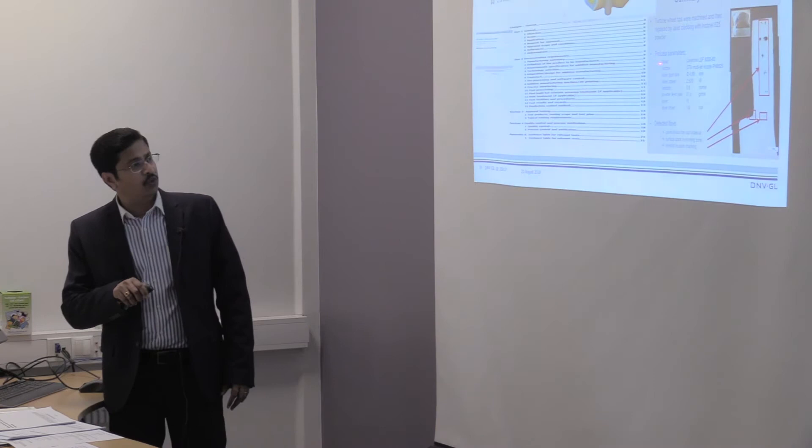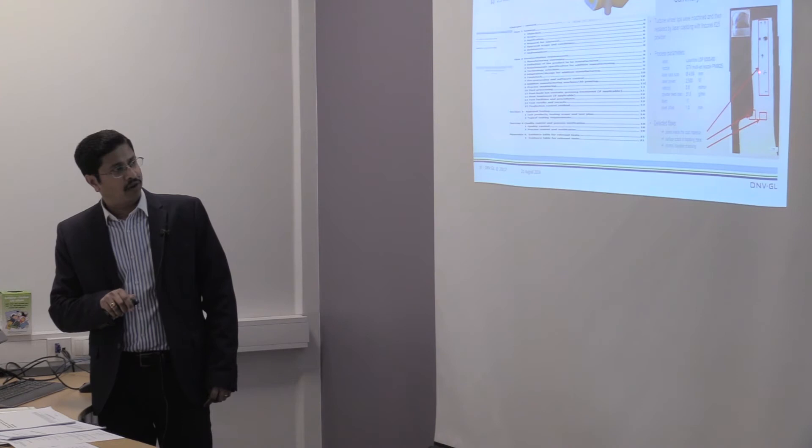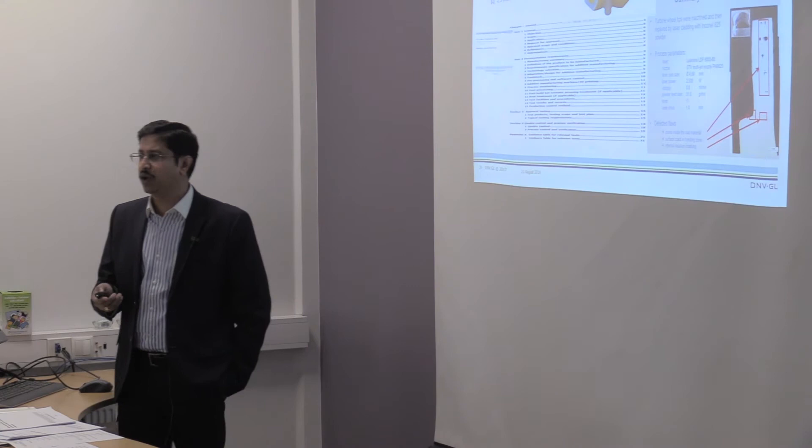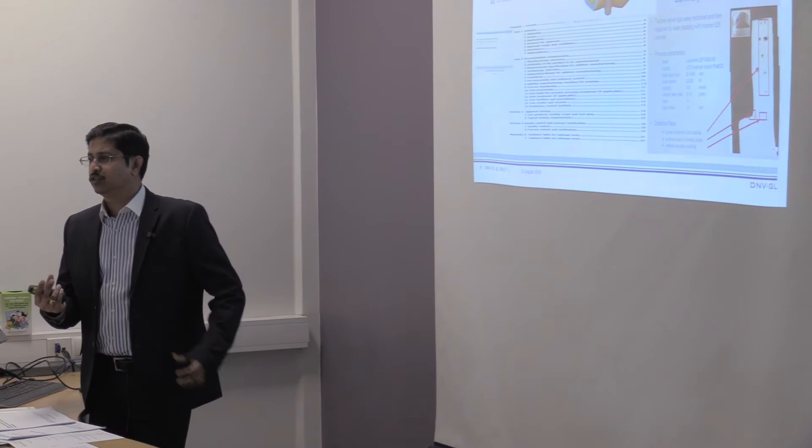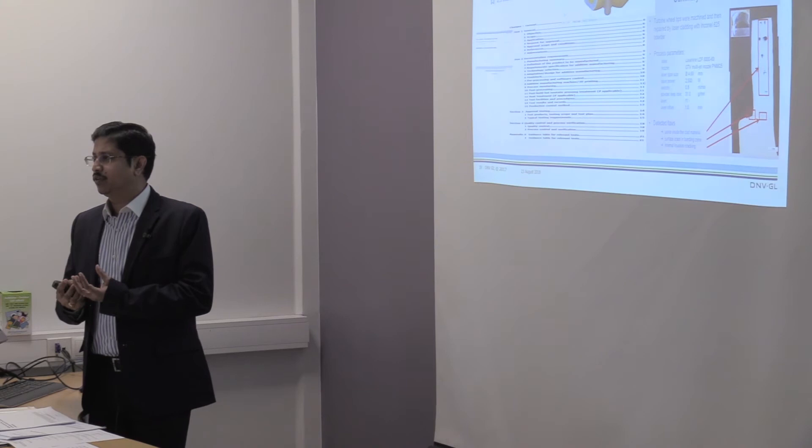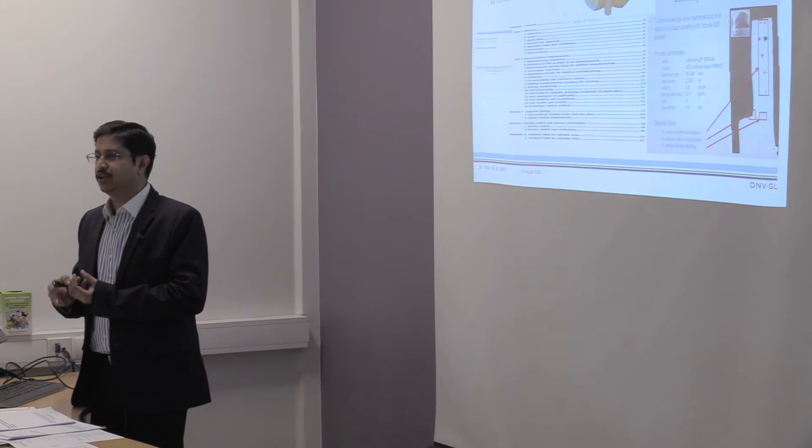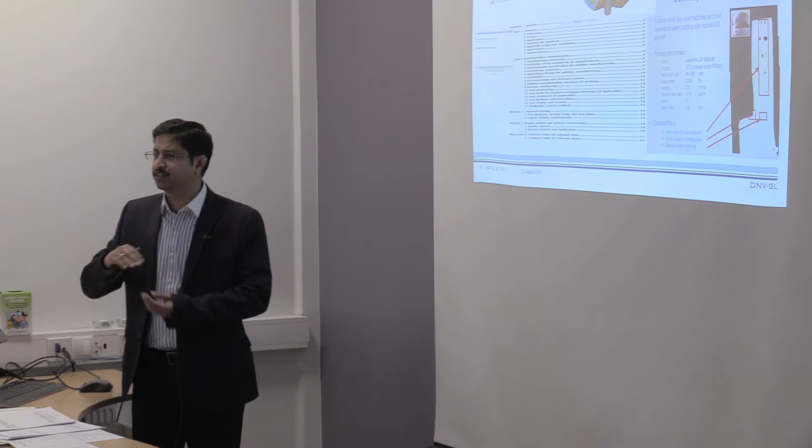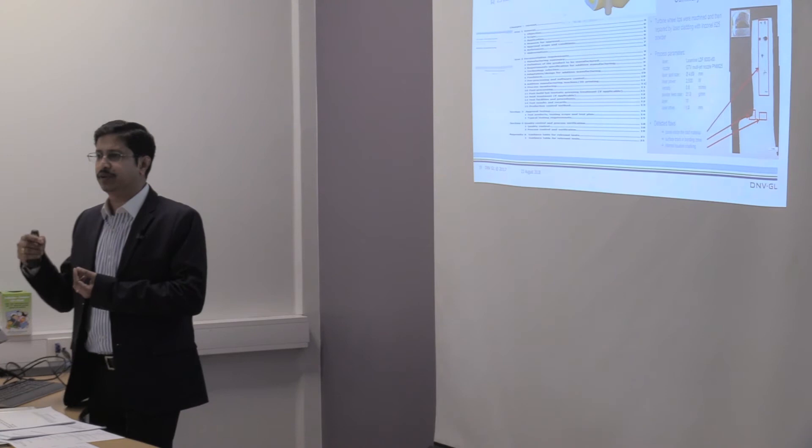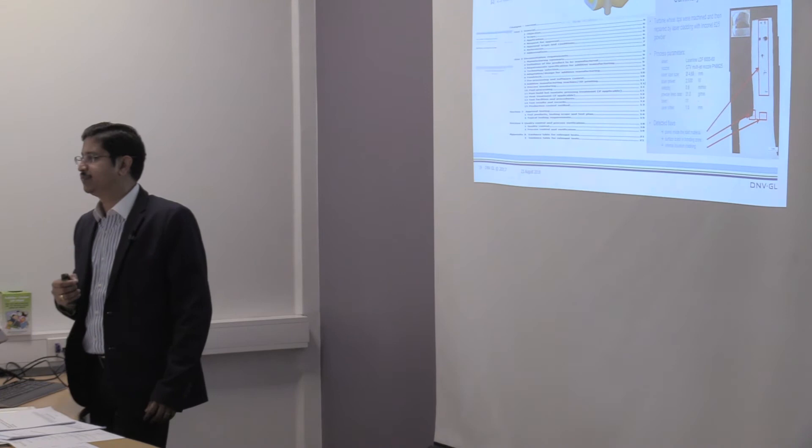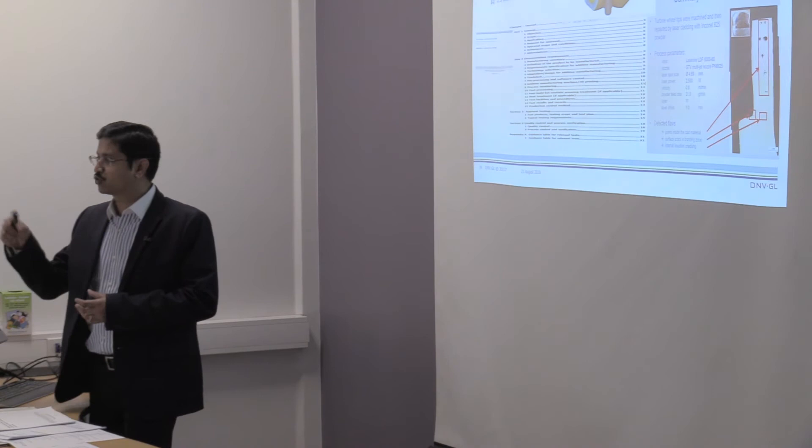As see this is one of the project we done, we find lot of pores here as well as we had some surface cracks in bonding area and liquidation cracking. So, it is not simple that we see that if you have additive manufacturing, you can produce a product, but we need to do lot of study in that. So, when you are qualifying itself, it has to have a very clear records. If you do not have the records and the computer is not taking up the information of the what is the how many data and how many layers, it will be difficult. So, we need to monitor the each layer wise. So, for this case it was said that they will have a 3000 slicing layers. So, each layer has to be monitored by the software. So, if there is a surge in the electric current, if the amps or voltage is having some fluctuation, that is also going to create some defects. So, all has to be perfect as in industry 4, you are showing all the parameters that is one of the main thing.